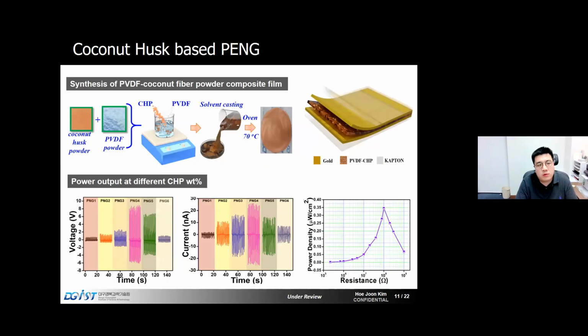And what we did next was that we combined this coconut husk powder with the piezoelectric polymer, PVDF. We simply mixed it, and then we cured it in an oven. And what you get is a coconut husk and PVDF composite film. This film is flexible and bendable, and it can also be poled by applying an electric field in the vertical direction. So you can make this film-type piezoelectric device where electricity is generated when it is pushed,